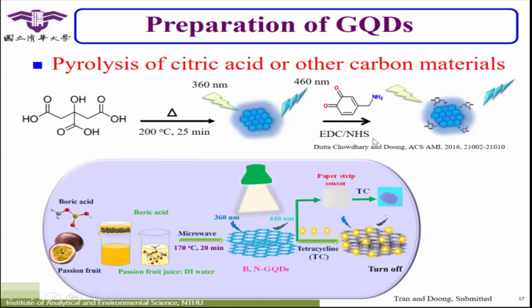Every country has agricultural waste, like passion fruits, coconut juice, apple juice, or citron. All of these contain a lot of citric acid and some sugars, glucose and others. For example, in my lab, I just used passion fruits, got rid of the seeds, took the juice, and put boric acid inside. Still use the microwave at 170, 20 minutes, and we can get the graphene quantum dots. If you add the boric acid, you can get the boron-doped graphene quantum dots.